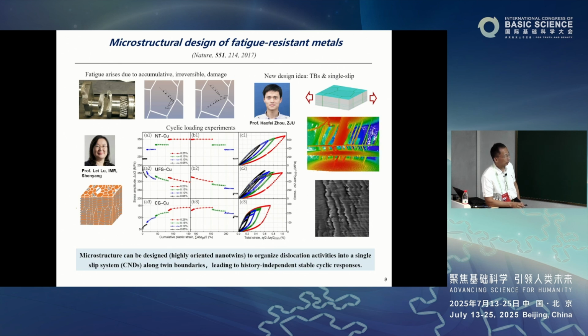The dislocations only travel like trains or cars on the highway, or trains on the railway. So they become highly organized. They do not entangle each other, so you totally avoid these intersection points. First of all, the dislocations all move parallel to the boundaries. They do not intersect with the boundary. Second of all, there is only one single slip system. You do not have a multi-slip system.